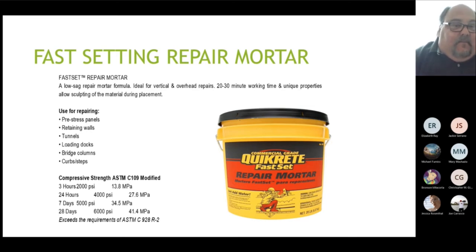With this one, you mix it up pretty quick, no more than you can use in about 15 minutes. Otherwise, you'd be tossing around a bunch of boulders in a bucket. And just put it in the space, screed it off. It doesn't matter if it's overhead or vertical like a curb, because it doesn't slump. It doesn't want to sag down. You can actually sculpt the edges of it.